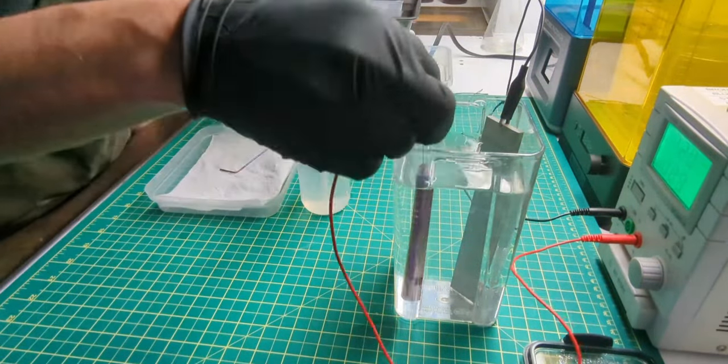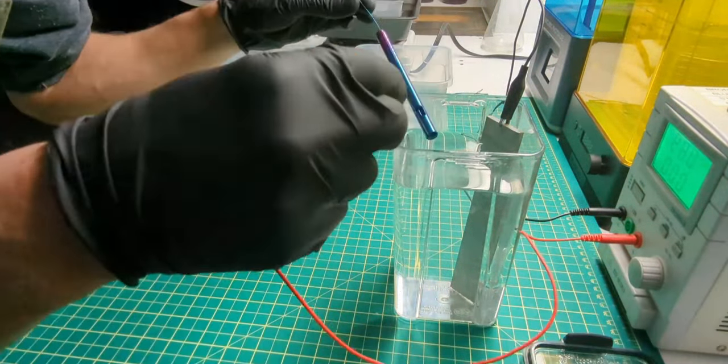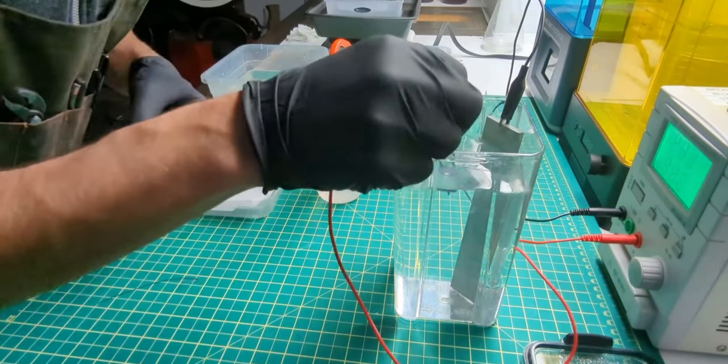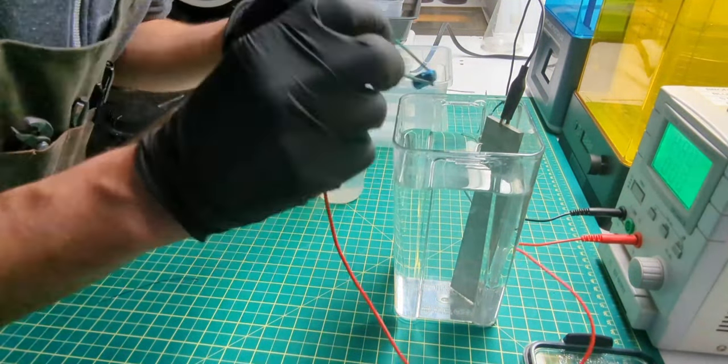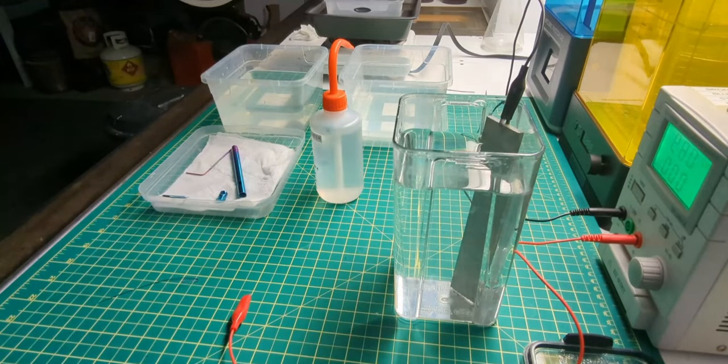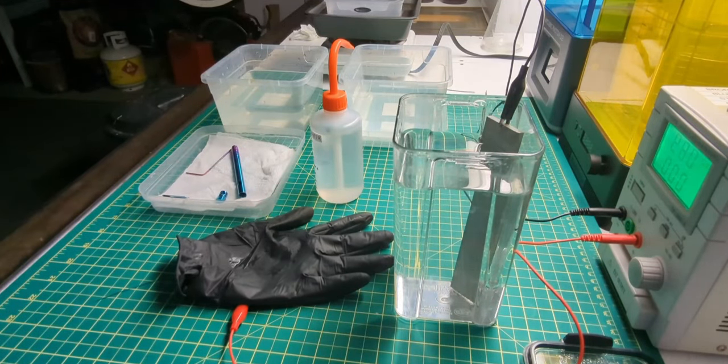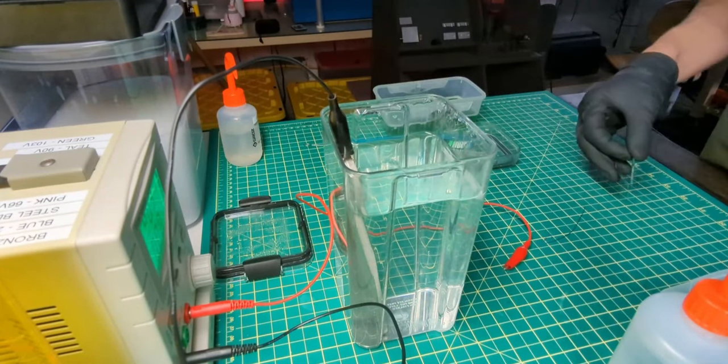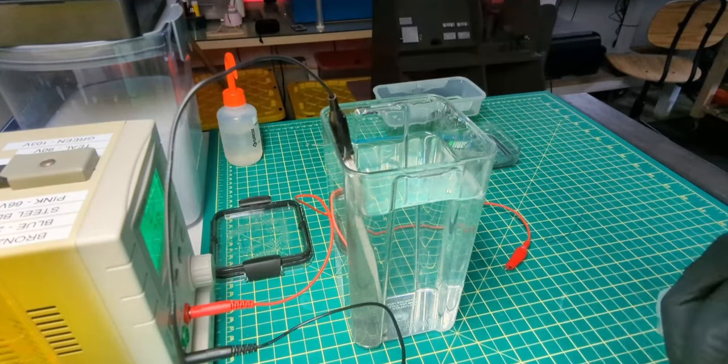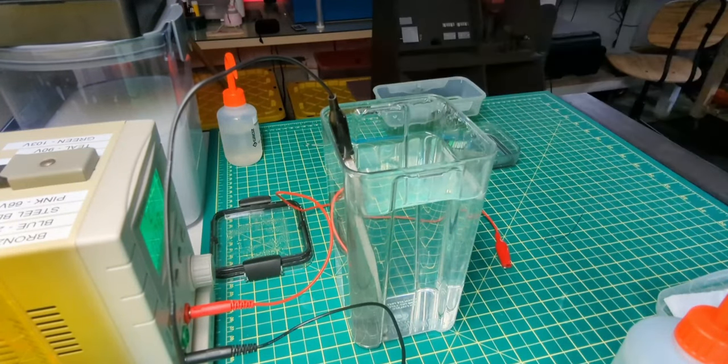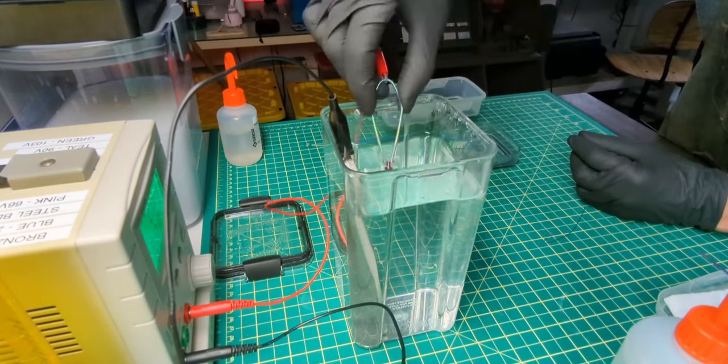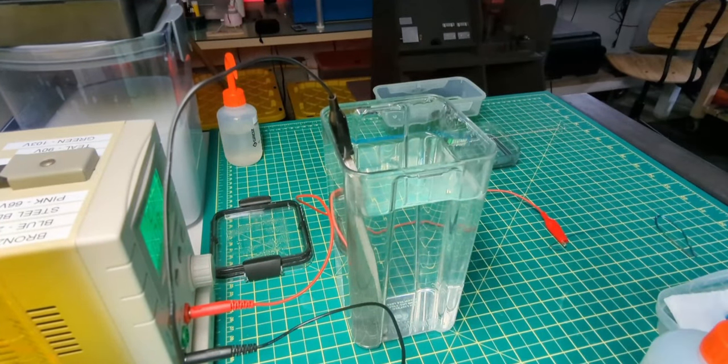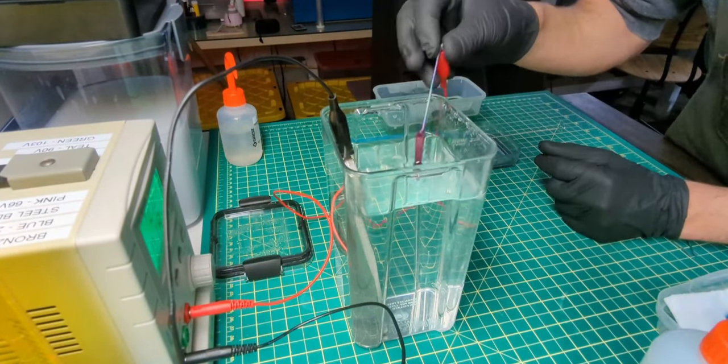Go through all the anodizing stages. Here we're going to bring it to a purple. It's the first color in the fade and then we're going to fade it up to teal. I'm fading it really quickly. You can see just the end is purple and it fades quickly to teal. That's because this is going to be an inverted pen, so most of that anodizing layer is going to be stripped off and I want the whole pattern to be visible in the grip, which is why it's in such a narrow band. Next we just color match all the parts. They don't match perfectly at the same voltage, so there's a little bit of fine adjust to get them visually perfect. And that's part of the reason the fade anodized pens cost the most, is just doing the color matching.